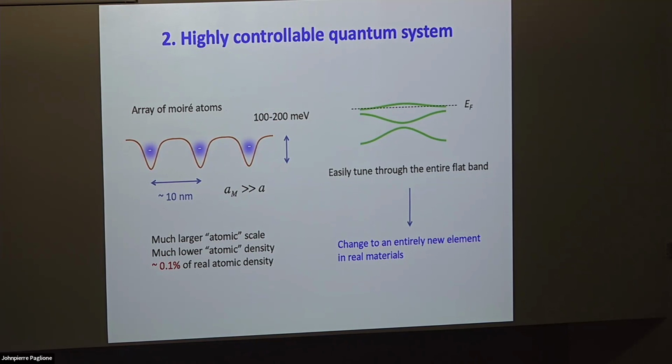And it's in that sense that you can build an artificial Moiré periodic table, because the first electron has to go to a spin up state, let's say, of the s orbital. The next should go to a spin down state of the s orbital. Then the next will go to a p state. But it's two dimensions, so your m is only 0, ±1, or ±2. So you have to make your periodic table different from this 3-dimensional periodic table.